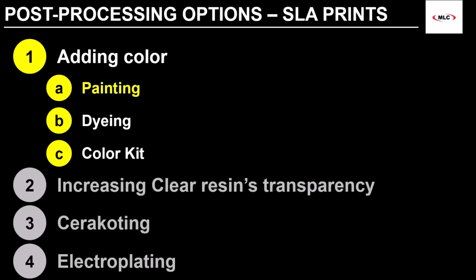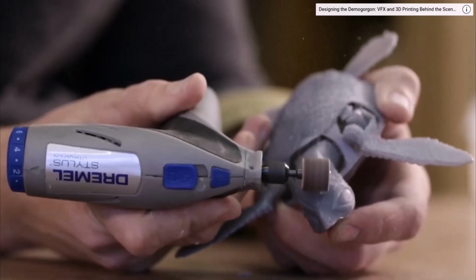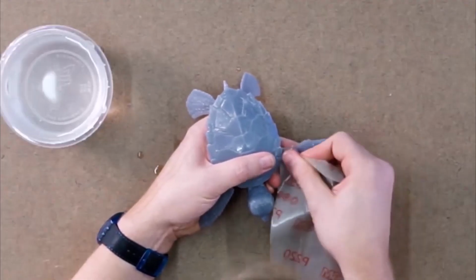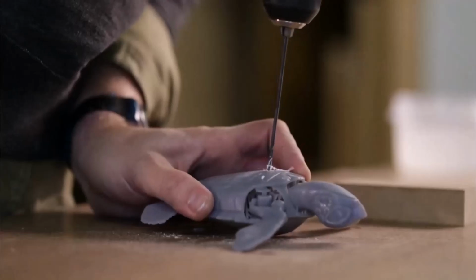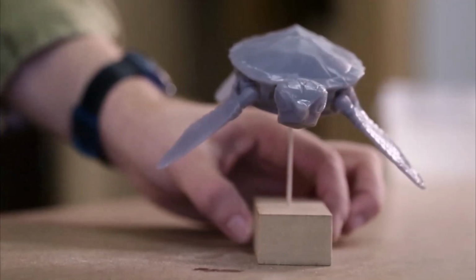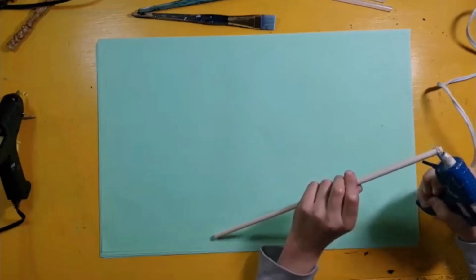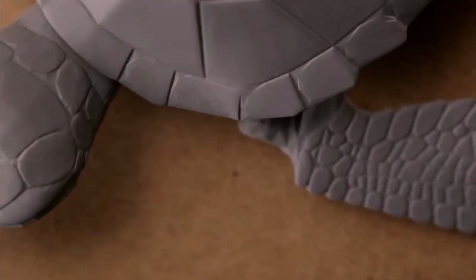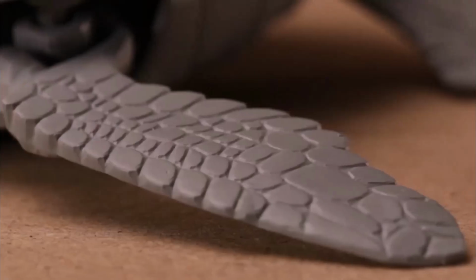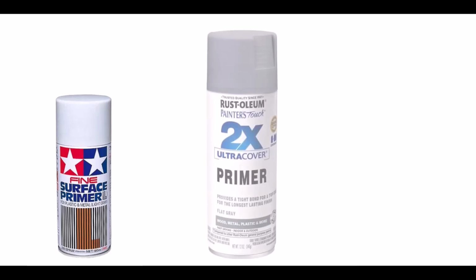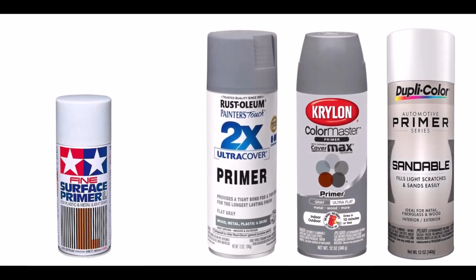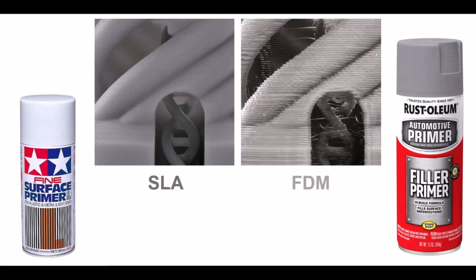When preparing to paint any plastic part, you want to first go through the preparatory steps that we just discussed. Then, it's a good idea to mount the part in preparation for priming. This can be done with either drilling a hole into the part or using hot glue to mount the dowel. Priming is a good practice because it helps to expose surface flaws and increase top coat adhesion and durability. Tamiya surface primer is really great, but primers from Rust-Oleum, Krylon, and Duplicolor also work. And these are just regular primers. Since SLA prints have no discernible layer lines, you don't need filler primer like you do with FDM prints.